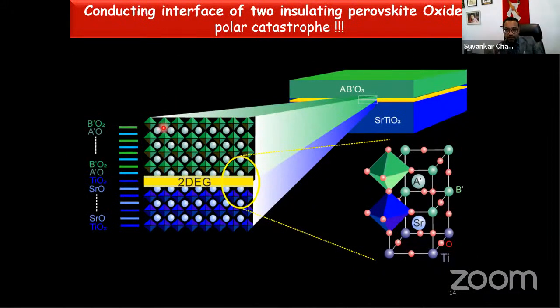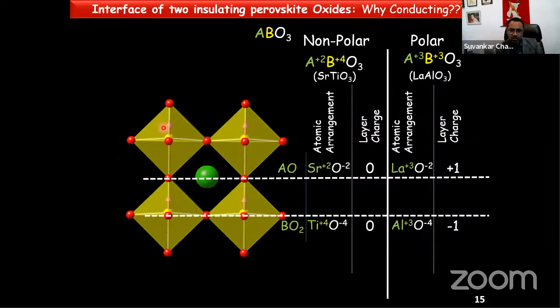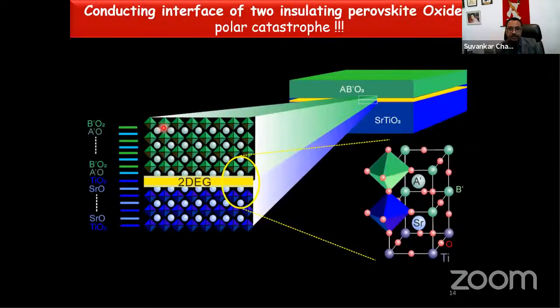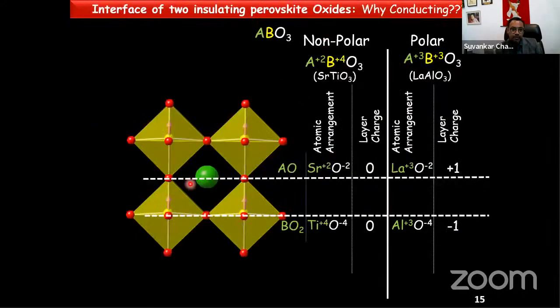So just to give you an idea why this kind of interface of two oxide insulators becomes conducting, many mechanisms have been proposed, but one of the well accepted mechanisms is what is known as polar catastrophe. If you think of a perovskite oxide and look into each layer, each layer contains either BO2 or AO atoms. If you think of strontium titanate, then this BO2 layer is a charge neutral layer, and the AO layer, which is the strontium oxide layer, is also charge neutral. But if you think about lanthanum aluminate, then this BO2 layer, which is aluminum oxide, has a -1 charge, and the lanthanum oxide layer, which is the AO layer, has a +1 charge.